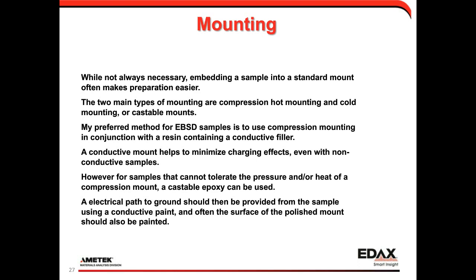However, it's important to note that not all samples are going to be able to take the pressure and heat of a compression mount. I've certainly had experiences of accidentally recrystallizing a few heavily deformed materials using a hot mount material at 160 C. And so in those cases, a castable epoxy can be used, and it has a lower curing temperature than some of the hot mounting materials. And so no matter what we use, we want to make sure there's an electrical path to ground from the sample to the SEM ground. And so you can use conductive paint, conductive tape, something to make sure that we have a path to ground because we don't want the charging artifacts.